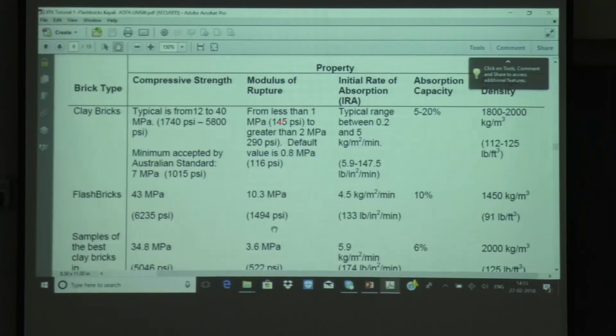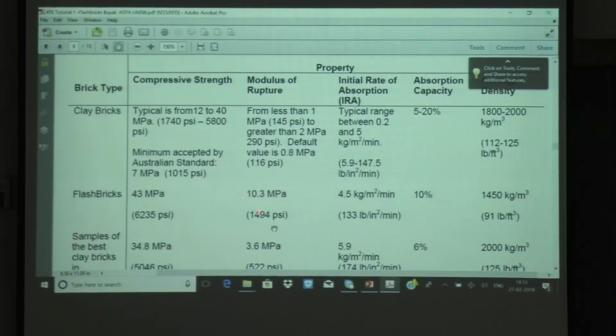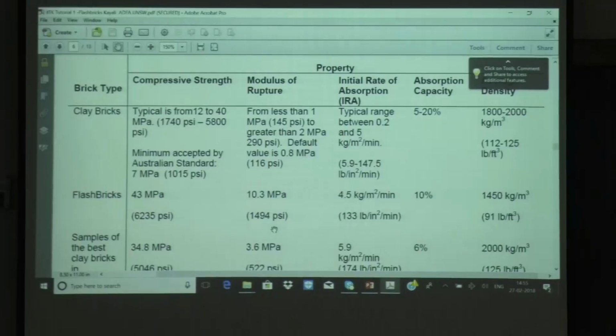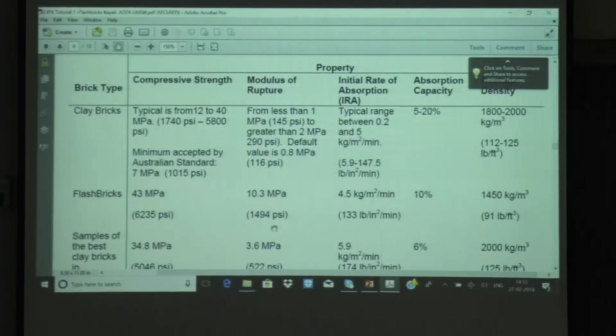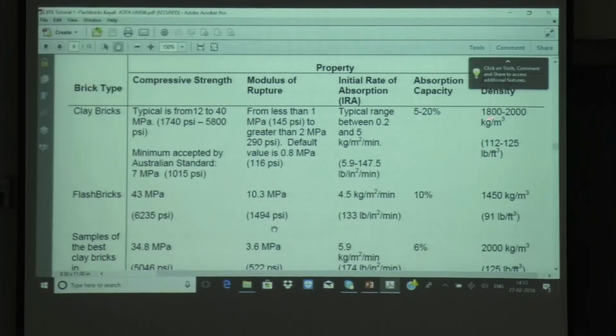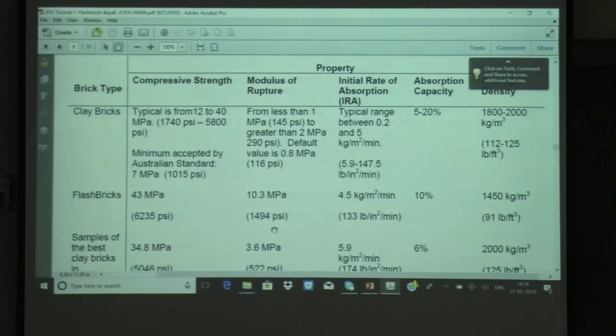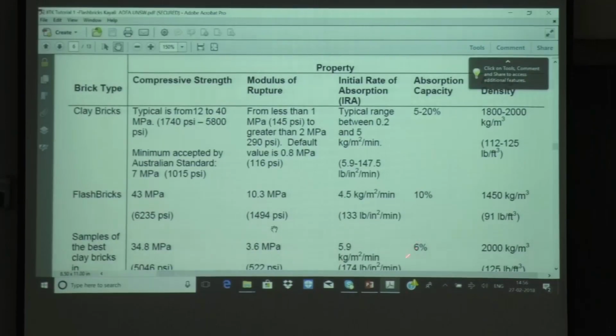Modulus of rupture for clay bricks is 1 to 2 MPa, whereas here it is 10, so about 5 to 7 times. Then typical initial rate of absorption here is 4.5. So it's quite good. Then absorption capacity is 10%, which is within the range. So it matches the ranges. And density, this is slightly heavier for clay, 1800 to 2000. This is about 1450, so it is about 20 to 25% lighter. Now the sample of the best clay bricks, as they say, is at 34.8, and then 3.6, 5.9, water 6%, but the density is still about 2 grams per cubic centimeter.